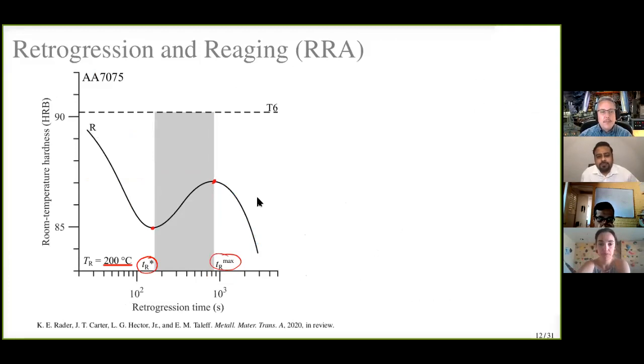There we go. So we have this process going down, and that's the initial dissolution of the fine eta prime precipitates primarily. So we're losing strength as we lose those precipitates, but we're also coarsening some of those eta prime precipitates a little bit and transforming some of them to eta precipitates. And we get some strengthening effect from those finer eta precipitates, and that's what's giving us the strength here. This second peak is that everything is now getting pretty coarse and we have over coarsening. So this is kind of everything is now getting too coarse.